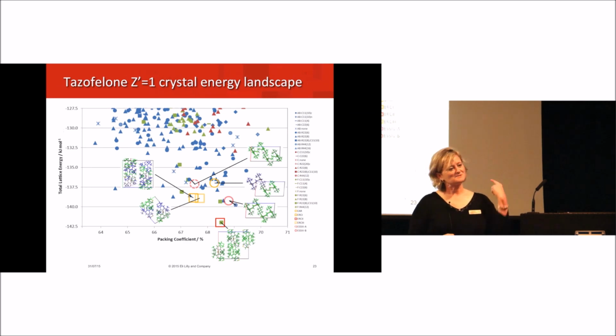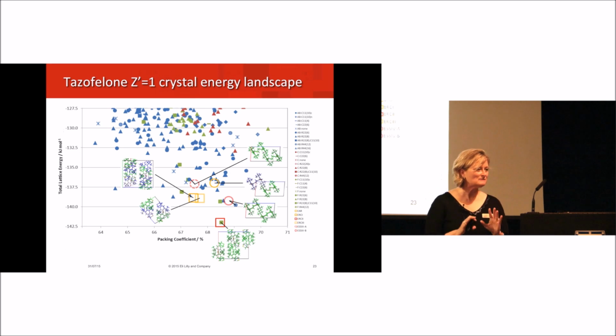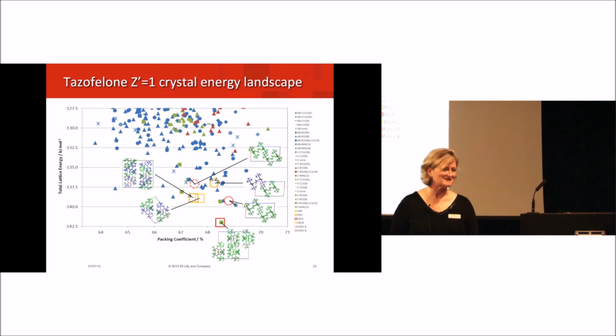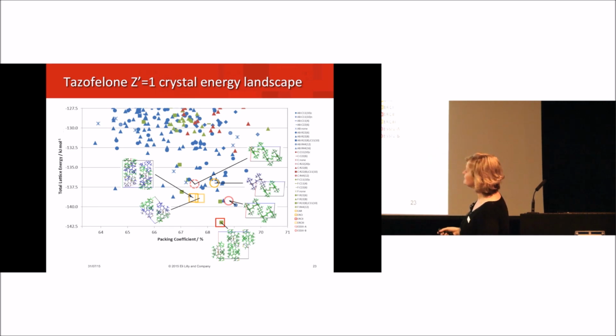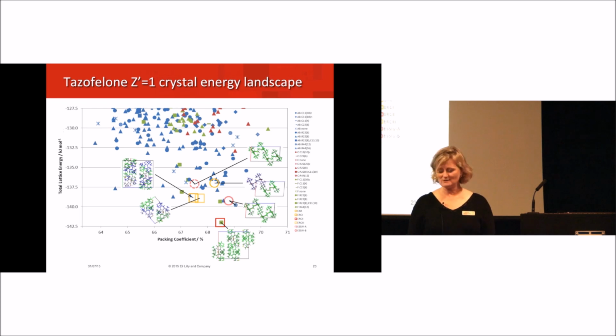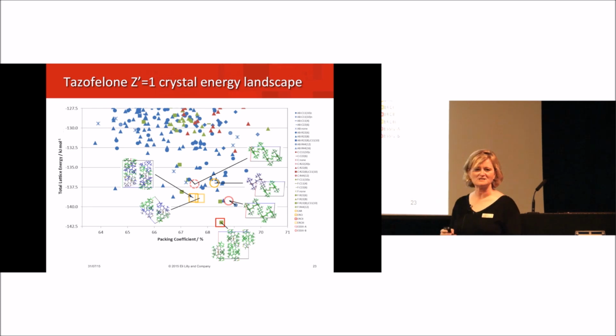This is Sally's crystal energy landscape, and this is probably the best case scenario. This is the scenario where the forms that we have found, whether they're Z'(1) forms, which would be found in the search, or Z'(2) forms, which are not in the search, all represent a good chunk of the structures in the low energy region. So for those of you who are less familiar with the crystal energy landscapes, each dot represents a crystal packing ranked by the lattice energy and the packing efficiency. In the best case scenario, you have low energy, highly efficiently packed crystals, and that's a good thing. And so this was really great, although I will tell you, when you have a compound that you think you know a lot about, and then Sally shows you all of the things you haven't found, it is rather nerve-wracking, right?